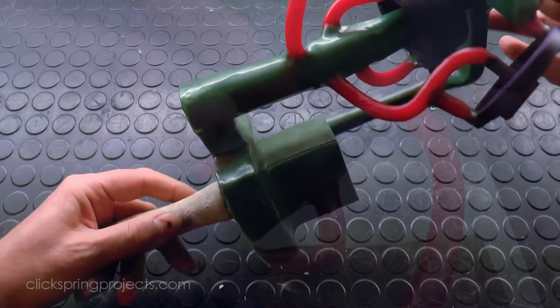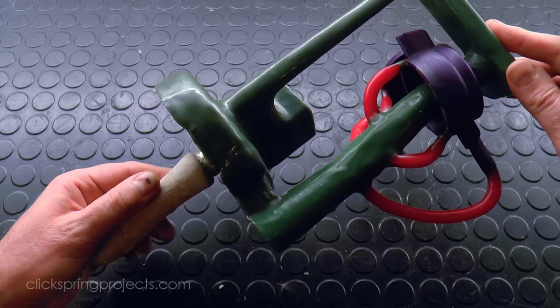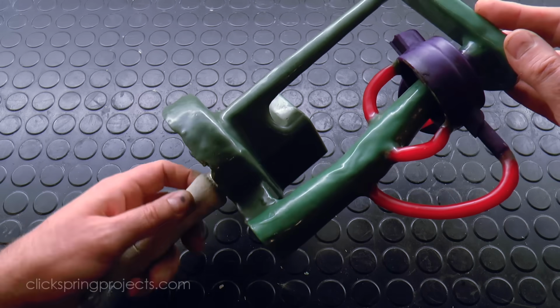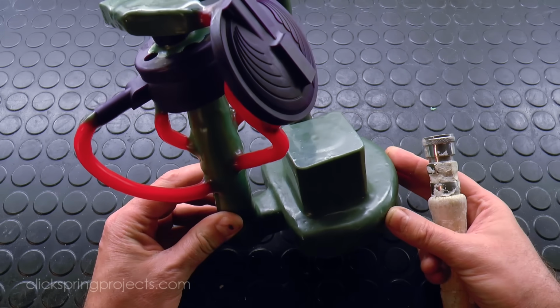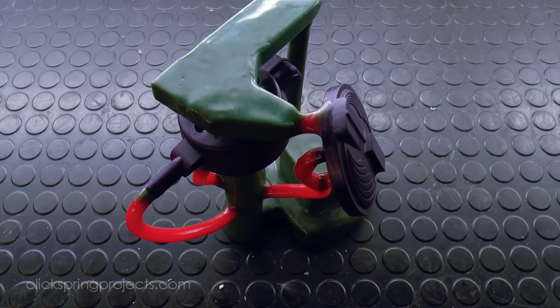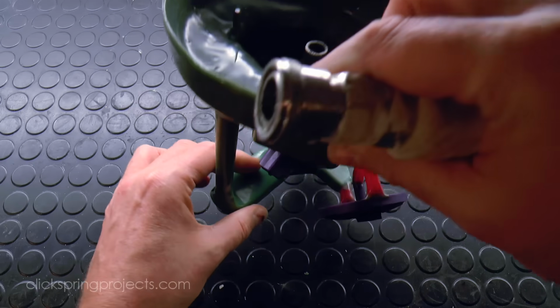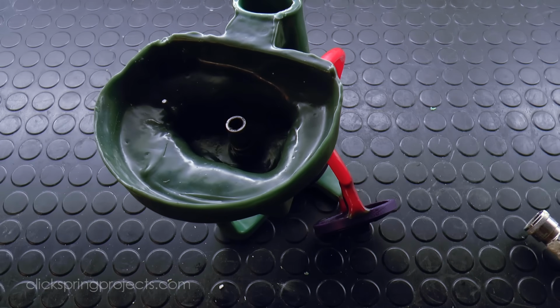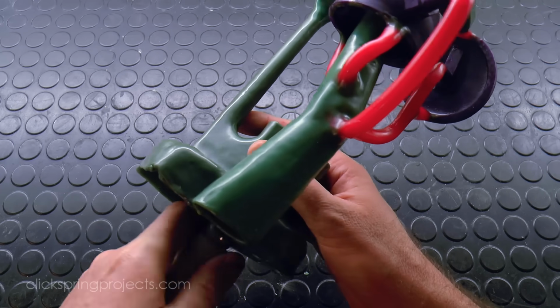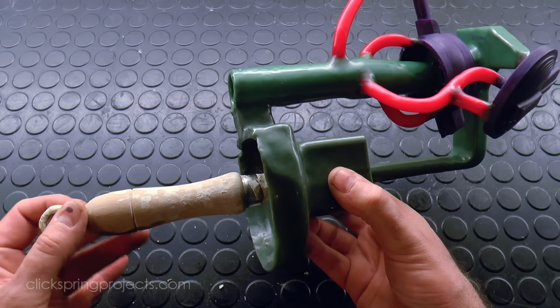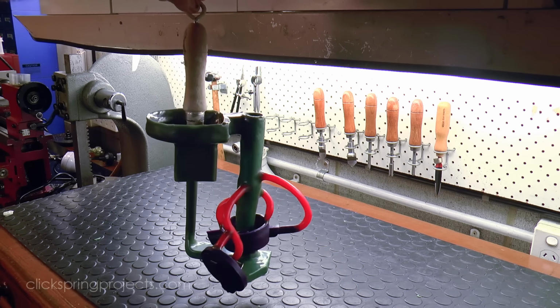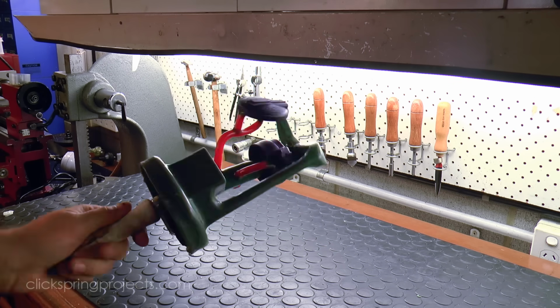The handle pops on and off easily, and the wax elements of the mould are designed to make sure that the mould is stable in both the upright and inverted positions at all stages of the process, but most importantly when placed in the kiln for firing. The handle also serves as a convenient way to hold the mould upright for drying.